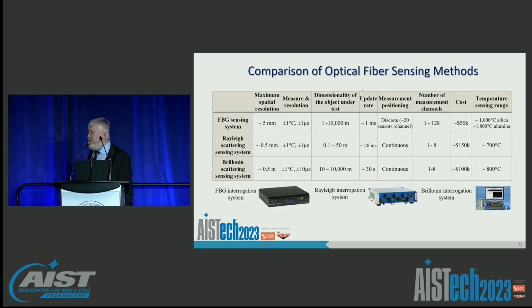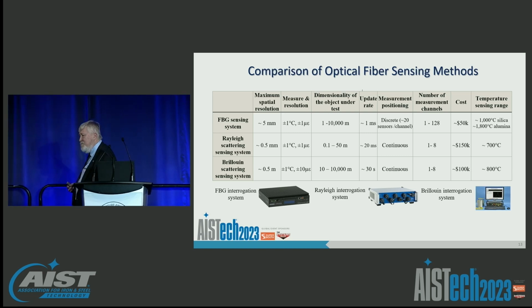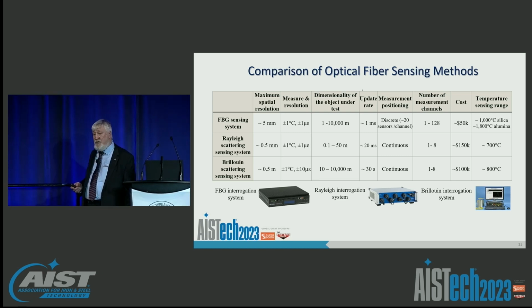Many systems that I see out there are limited to 50 or 60 sensors on a fiber. But with that, you can go over very long distances and do point temperature measurements. So it's kind of a quasi-distributed measurement system. Temperature or strain can also be measured.